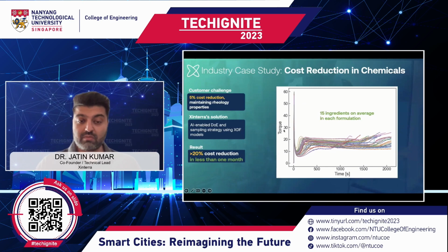And so what they gave us was this torque time curve, basically a rheology curve, and told us to maintain the rheology curve. Of course, there were certain other features that we had to maintain, things like color, for example, linked to oxidation. And the target for us is keep the performance roughly the same within a certain amount of tolerance, and reduce the cost by 5%.